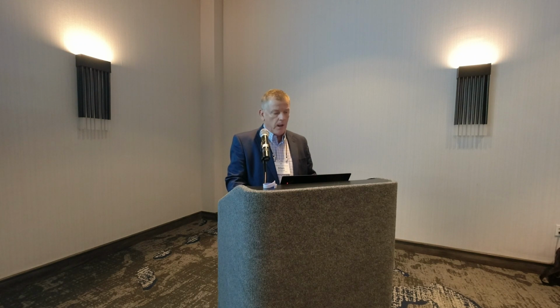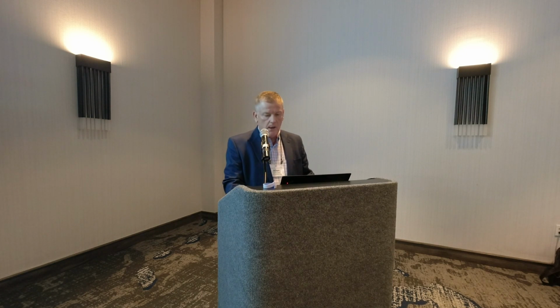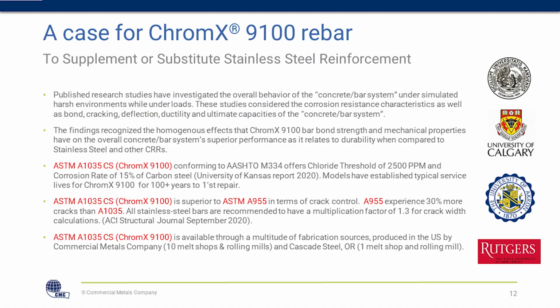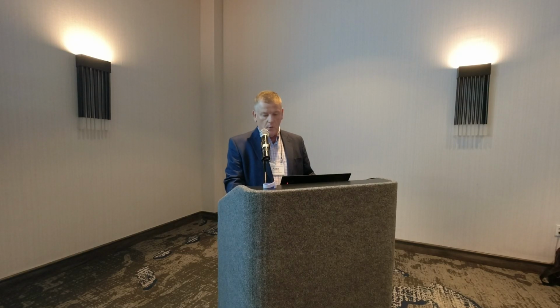So that's another part of what we'll be talking about throughout the day, just some of the cost variables and comparisons. Getting into some of their research, in 2019 they had a paper by the University of Akron where they did some bond strength testing and saw that they had greater results than stainless steel. And some of the other elements that we see here is in terms of chloride threshold. 1035 is 2500 ppm, and that threshold is about 15% of what carbon steel is. So it's a massive improvement over what you experience with carbon steel.